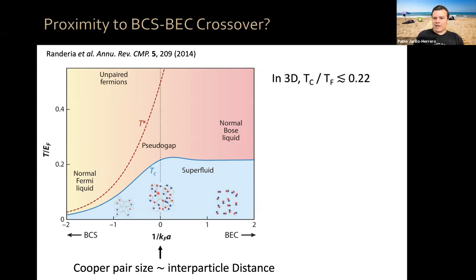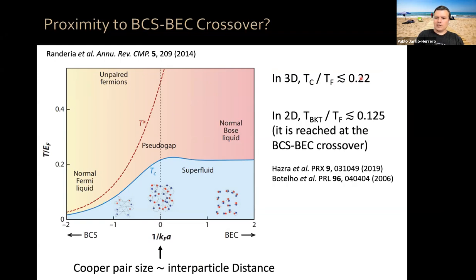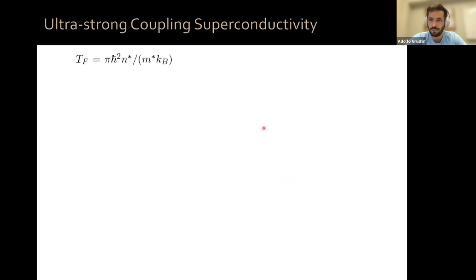Now, in three dimensions, there is a bound on the value of your critical temperature over your Fermi temperature, which is 0.22. Okay. In two dimensions, there is a corresponding bound on T_BKT over T_F, which is 0.125, and it is reached precisely at that BCS to BEC crossover, okay? Now, because we can, yep.